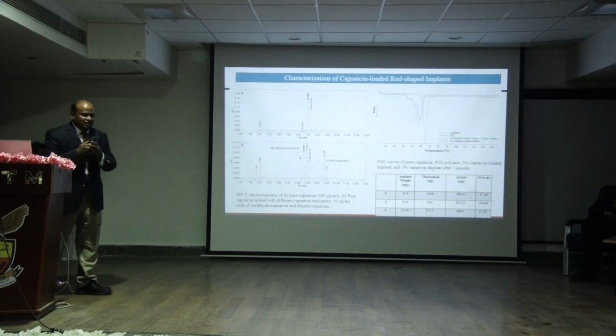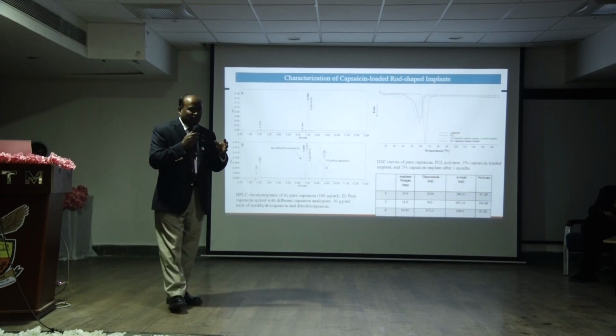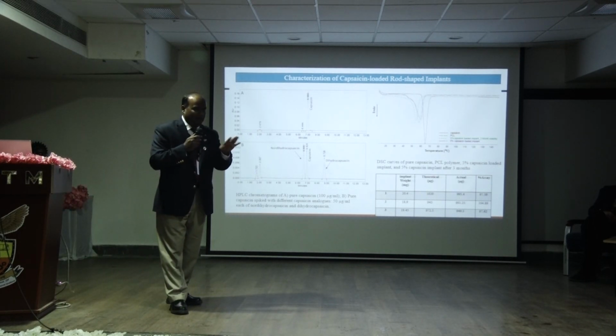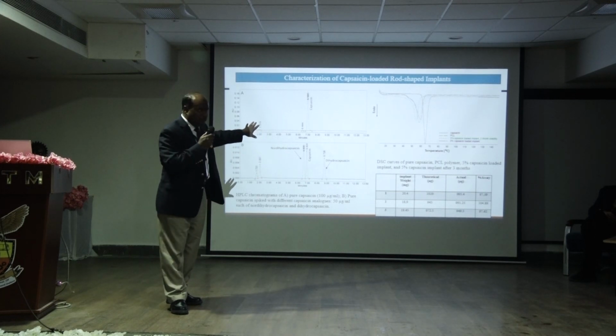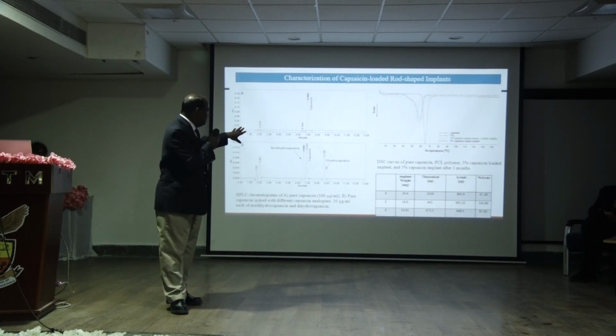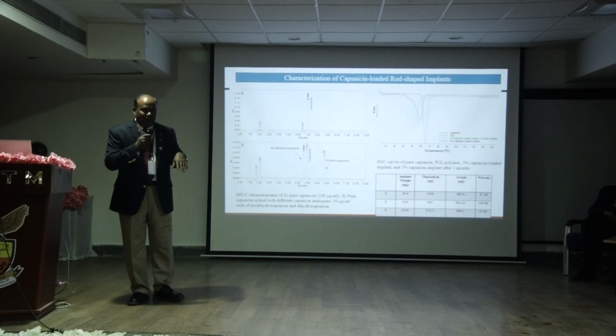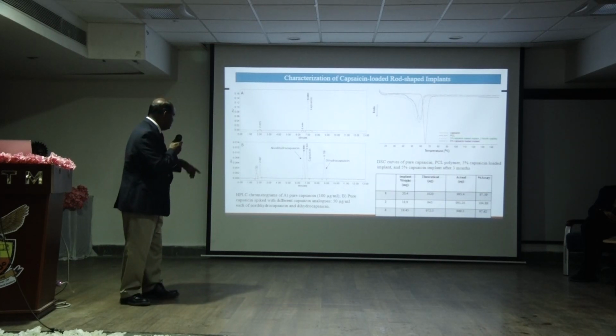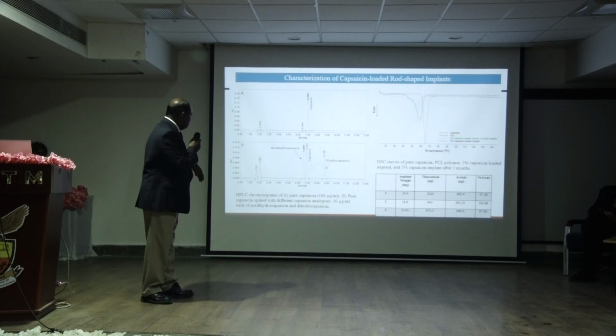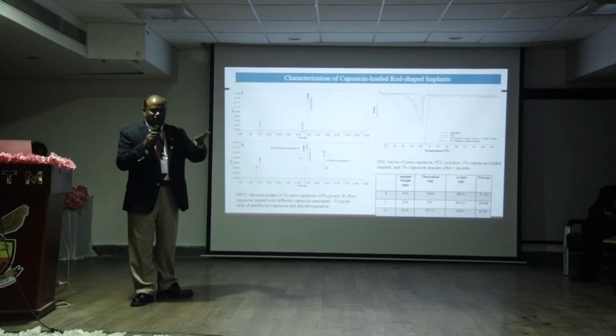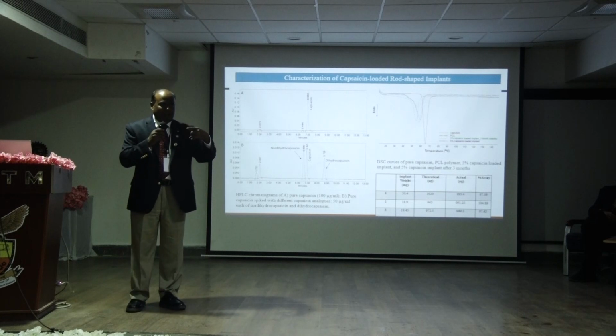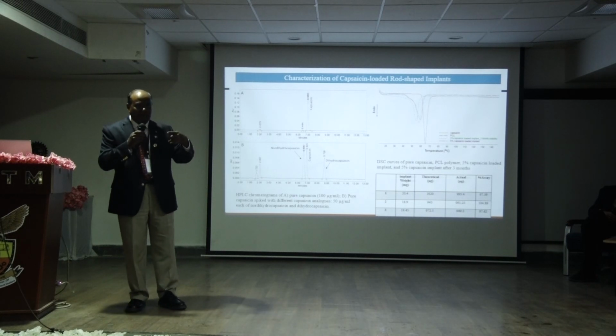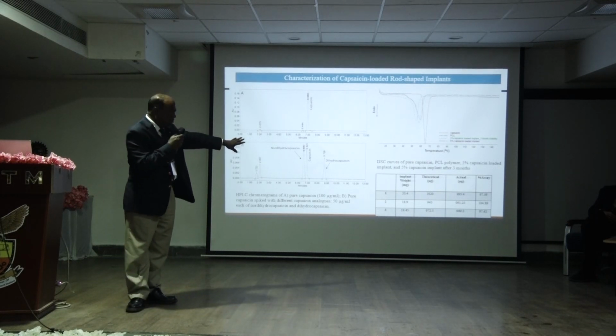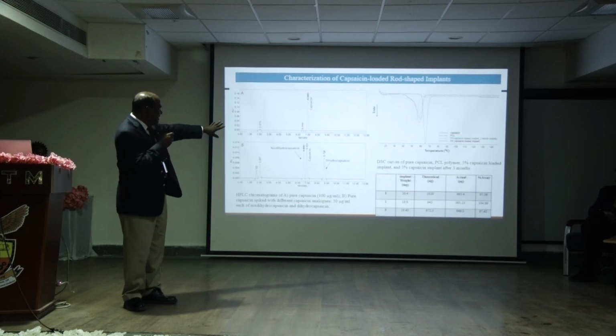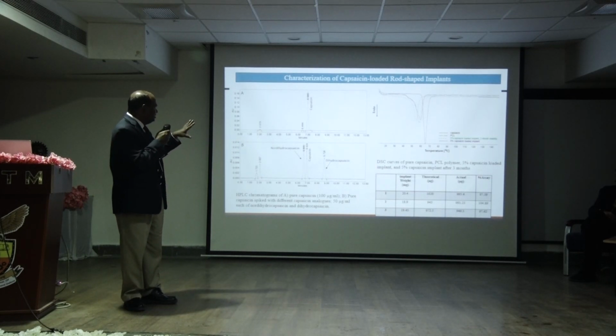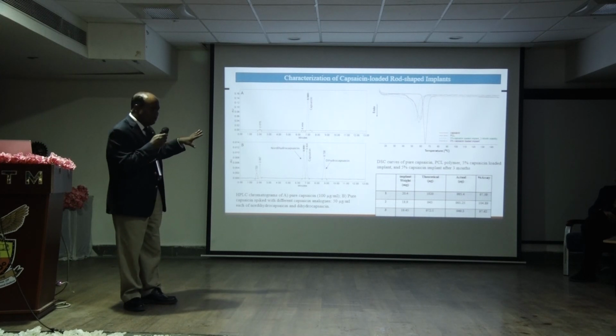So we did some characterization studies to prove that there is no drug interaction between capsaicin and the polymer. I'm wrapping up. This is the last slide, maybe one more slide. We confirmed with a drug assay that the drug is not degraded due to melting. We had to melt the capsaicin and polymer together, so we made sure that there is no chemical drug degradation and physical interaction with the polymer. The drug is intact and available for delivery.